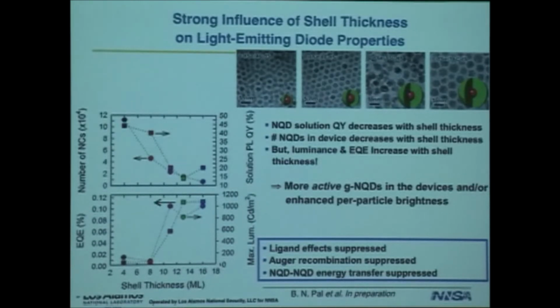And lastly, quantum dot to quantum dot energy transfer, which in a dense film of dots can actually kill your PL. You tend to transfer from high energy dots to lower energy dots. And also there's actually a paper out recently that suggests that the transfer is preferentially to trap-ridden dots. And so that process itself can kill you in the solid state in the case of quantum dots. And anyway, the thick shell systems have advantages in all 3 cases here.